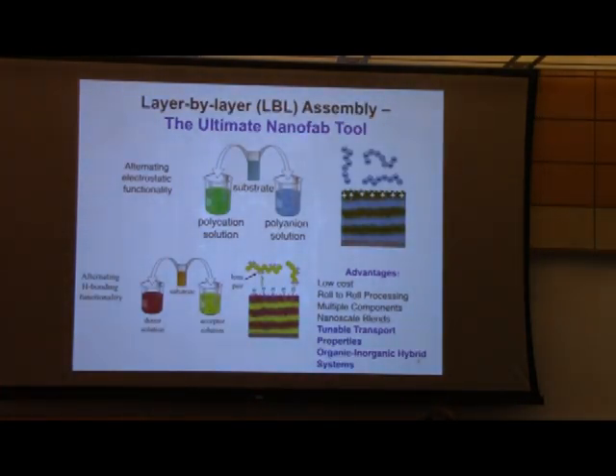The way this process works is that you start with a substrate, and it can be virtually any substrate: glass, plastic, a range of different films. And that substrate, as long as it has some sort of initial charge on the surface, can be immersed into a dilute aqueous solution that contains a multivalent charged species, any sort of material that has multiple charges. That charged species is going to absorb onto the substrate until ultimately that surface charge is reversed.